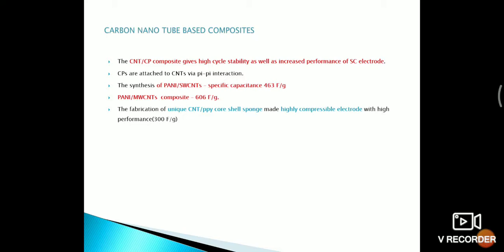This is carbon nanotube based composite. The CNT conducting polymer composite give high cycle stability as well as increased performance of supercapacitor electrode. Conductive polymers are attached to CNTs via pi-pi interaction, and the synthesis of polyaniline single-walled CNT specific capacitance is 463 farad per gram, whereas the polyaniline multi-walled CNT composite give a specific capacitance of 606 farad per gram. The fabrication of unique CNT polypyrrole core shell sponge made by highly compressible electrode with a high performance give a specific capacitance of 300 farad per gram.